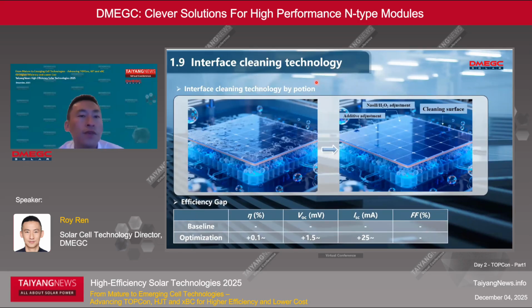And the interface cleaning technology. Interface cleaning technology works by polishing, mainly with chemicals or DI water. It will make the silicon interface cleaner and reduce the adsorption of impurities, further achieving a better passivation effect. So in this way, the Voc and Isc will be significantly improved. The cell conversion efficiency can be increased by 0.15%.